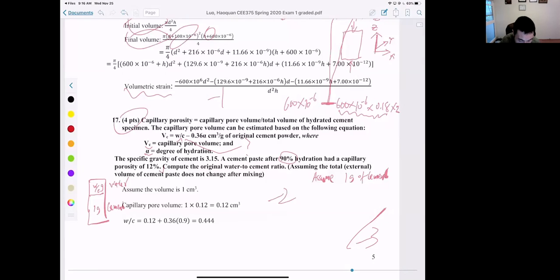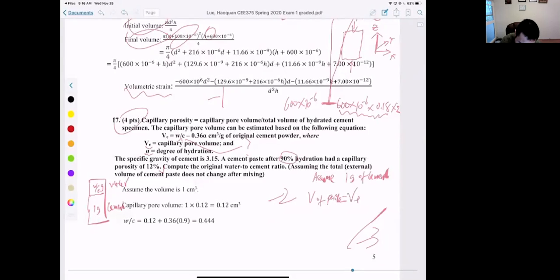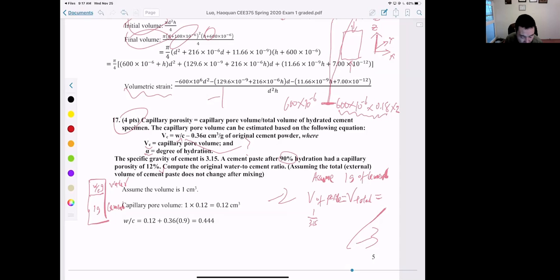We can calculate the volume of the cement paste. The total volume is equal to volume of water plus volume of cement. The volume of cement is equal to 1 gram divided by 3.15. This is the specific gravity of cement, which means for 1 cubic centimeter of cement, the weight is 3.15 gram. The volume of water is equal to the mass of water, W over C gram, divided by the density. The density of water is 1 gram per cubic centimeter. So this is the total volume of the paste.